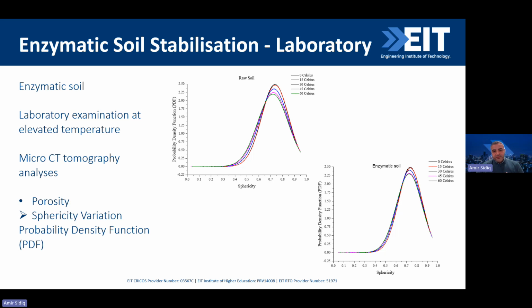For the enzymatic compared to the raw, we can see this variation is actually pretty constant at different temperatures, clearly showing it's controlling the shape of the void from moving from this spherical value of 0.7 or 0.75, for example, towards 0. So it's trying to control the shape of the void, which is really something we're looking for, because when external forces are applied, there are quite good repelling forces, which actually protect the structural behavior of the clay particles.